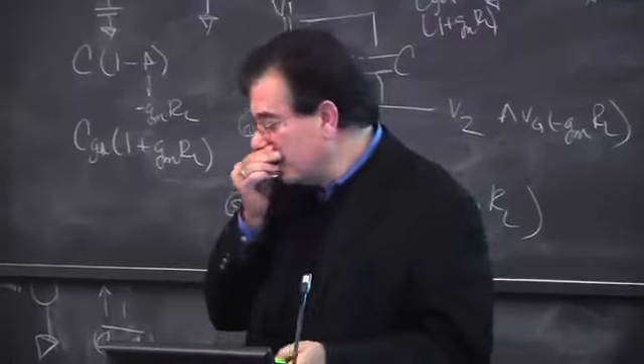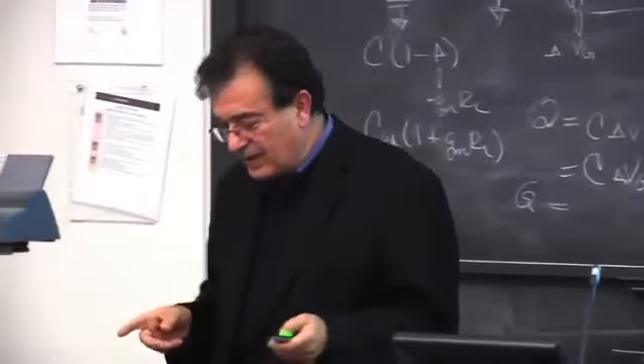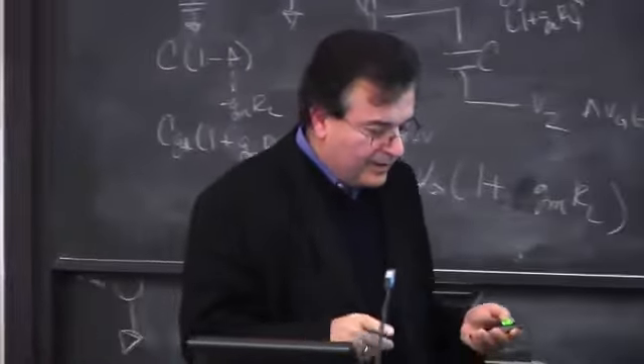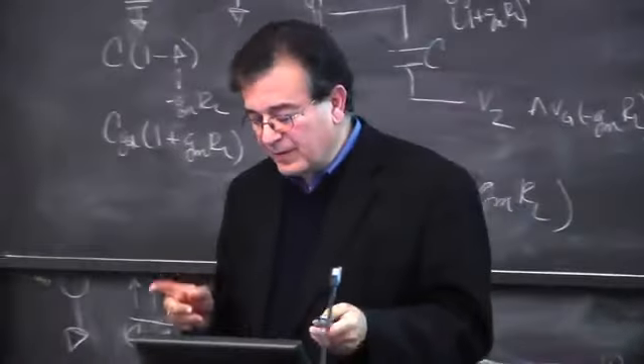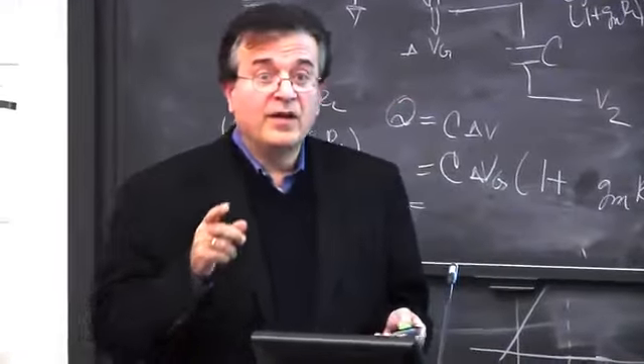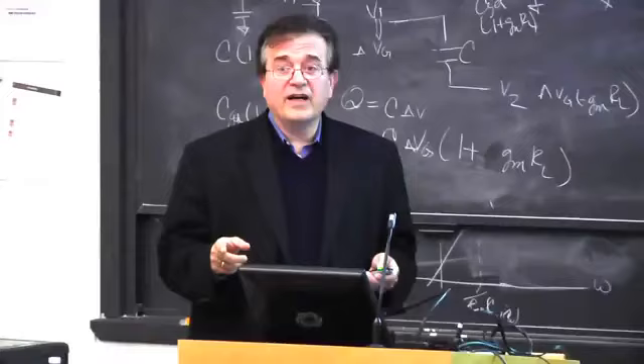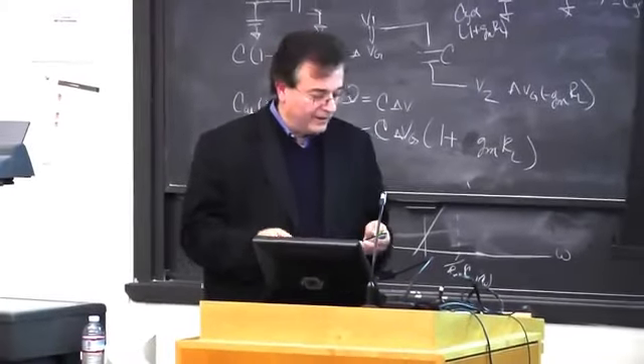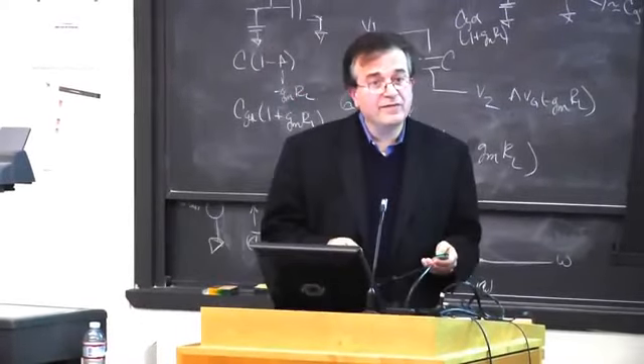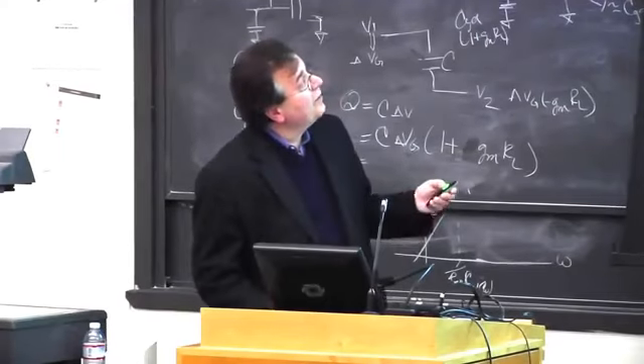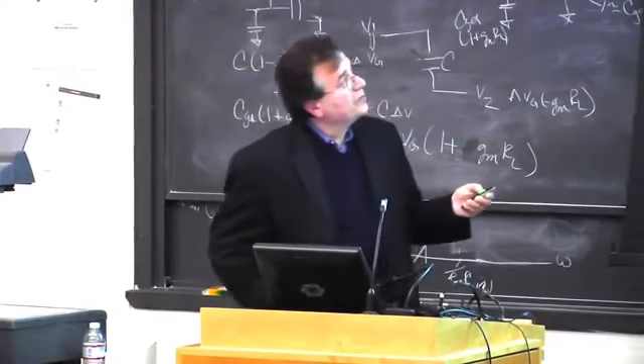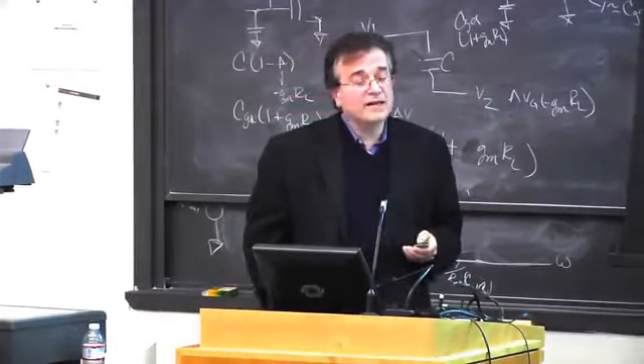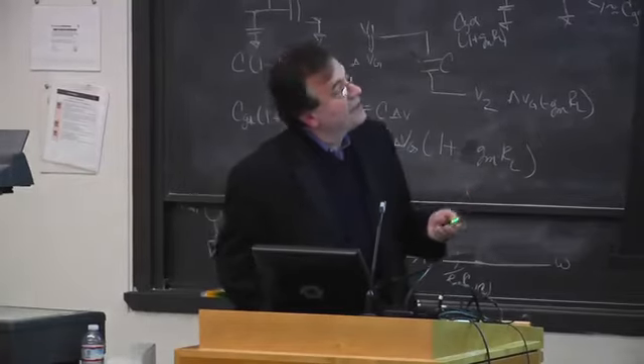So at that point, we thought this is why the thermal conductivity is very low. Vegard's law is not a good way to use as a diagnostic that you have a solid solution. So we published this somewhat provocative paper in JACS that we ended up with, the myth of solid solution.